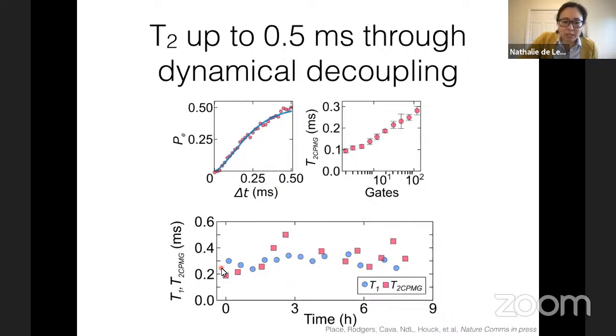Just to show you that we're not cheating, we can also look at T2, and we find that we have a T2 that's up to around half a millisecond if we do dynamical decoupling. And we can look at the time variation of these parameters. This might come as a surprise to anyone who works on atoms or even NV centers, but it turns out that transmons generally show a lot of variation on hour to day long timescales in their T1s and T2s, which is a really intriguing problem that I'd like to tackle separately. But anyway, to provide an honest comparison, we look at the time averaged values of all of these things, and we find that we really do have this robust improvement.